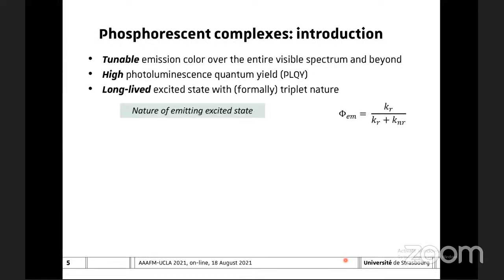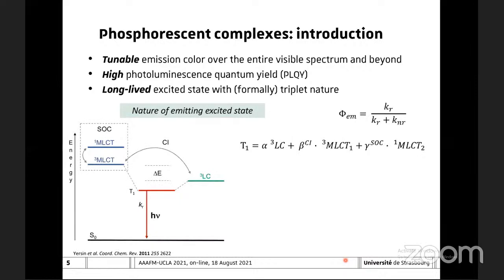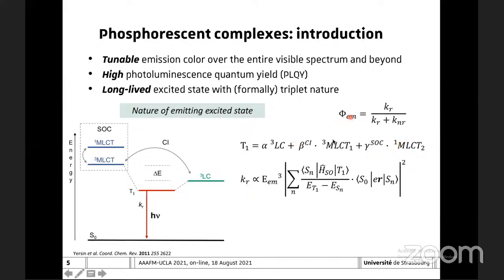So in those compounds, the emission of the excited state can be defined as a linear combination of three different states. So it's a combination of mainly triplet ligand-centered excited state, which mixes by a configuration interaction with a triplet metal ligand charge transfer excited state, and also by means of spin-orbit coupling with a singlet metal ligand charge transfer state. So the radiative rate constant, which is also linked to the photoluminescence quantum yield, is directly proportional to the third power of the emission energy, along with spin orbit coupling matrix elements and the oscillator strength of the compound.